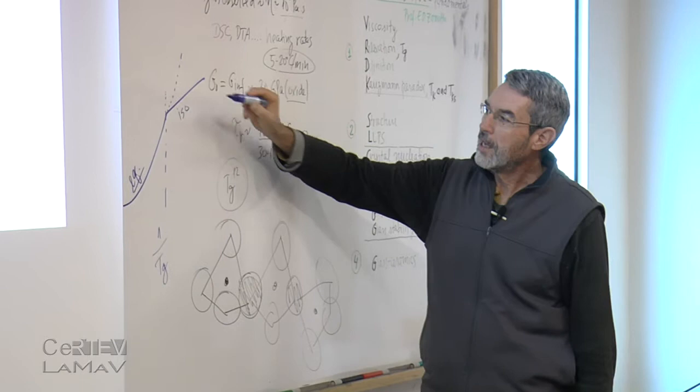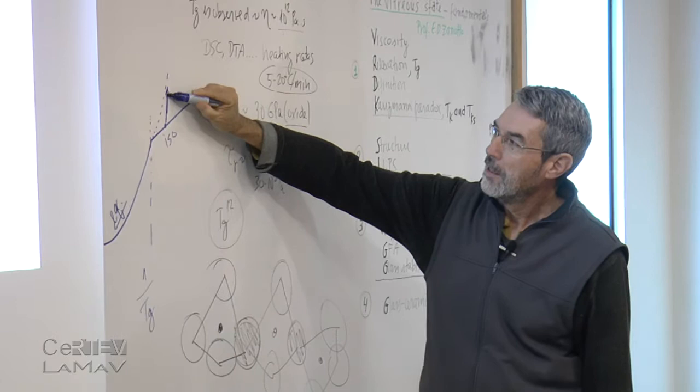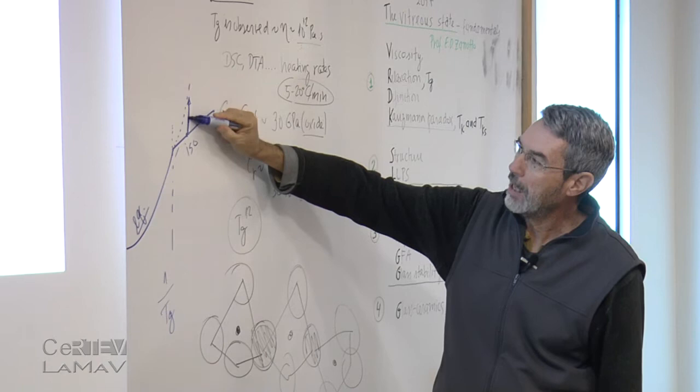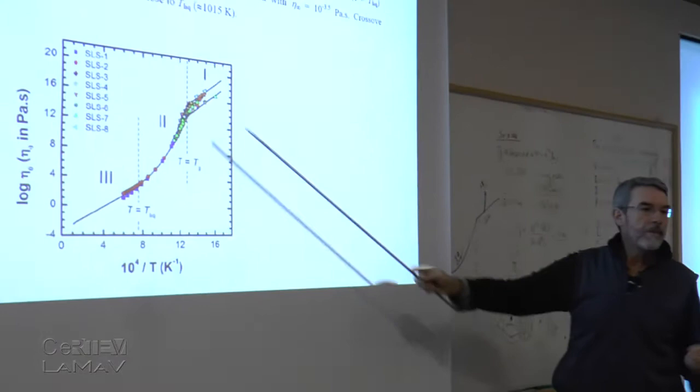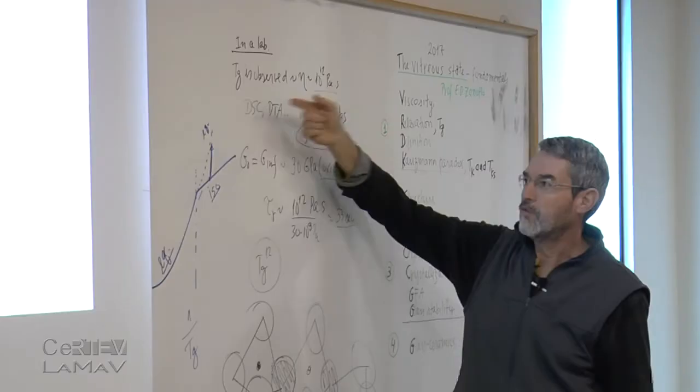Of course, if we take a long time here to measure the viscosity, the glass will relax and the equilibrium viscosity is given by the extrapolation of that curve. So this is that same relaxation phenomenon. From iso to equilibrium viscosity. This is relaxation. So one has to measure the viscosity faster before the glass relaxes. This is the isostructural viscosity.